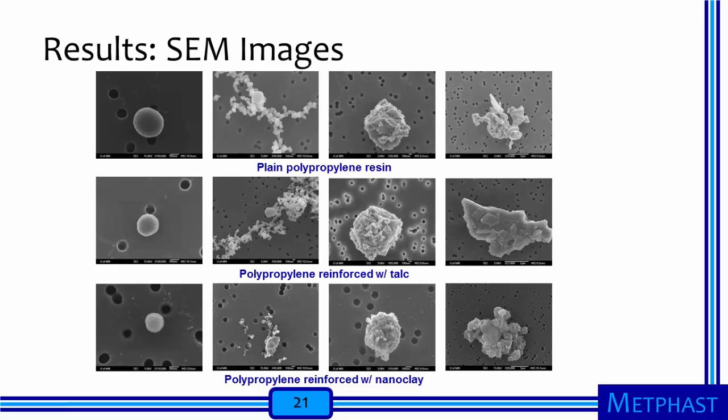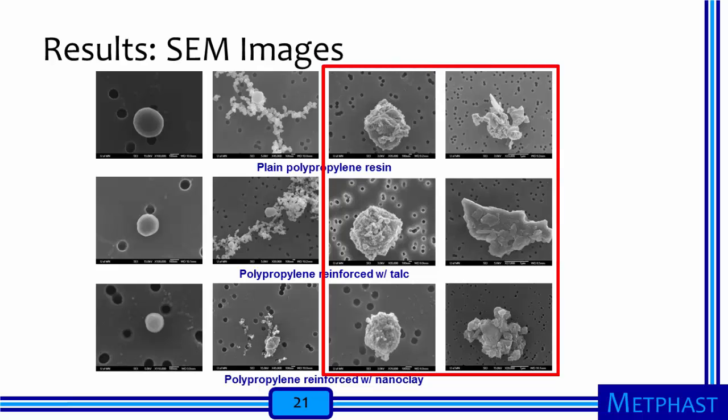Scanning electron microscope images of samples collected using the MOUDI impactor show that similar particles were captured from each of the three plastics as they were shredded. Individual spherical particles may be a result of volatilization of the polymer as it is heated by shredding, followed by immediate recondensation in the surrounding air. We also see chain agglomerates of spheres, as well as compact and more spread out aggregates of smaller particles.